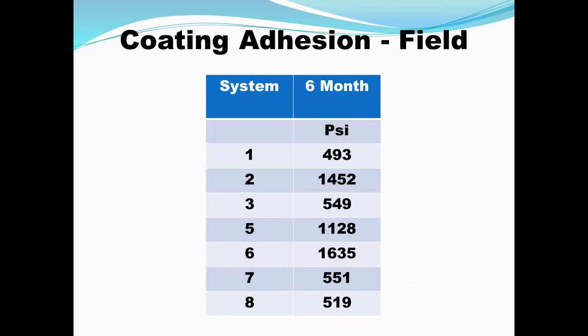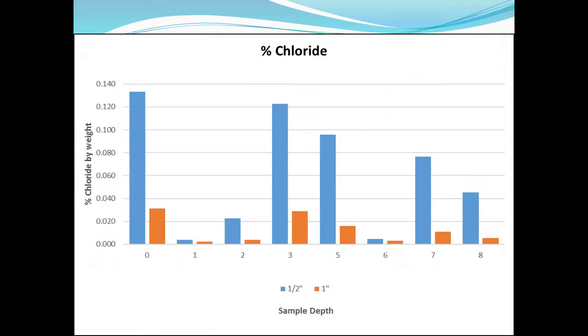This is the coating adhesion in the field. It was tested after 6 months. And again, same sort of numbers, 500 to 1500 PSI, all of them enough adhesion. Chloride: the salt ponding blocks went through the test protocol, and then each block had three locations where powder samples were taken and combined and evaluated for chloride contents at the half inch depth and 1 inch depth. And as you can see here, system zero over here is a control. No coatings, just bare concrete. And as you can also see, systems 3, 5, and 7 really didn't do much for retarding chlorides. Systems 1, 2, and 6 did a pretty good job.